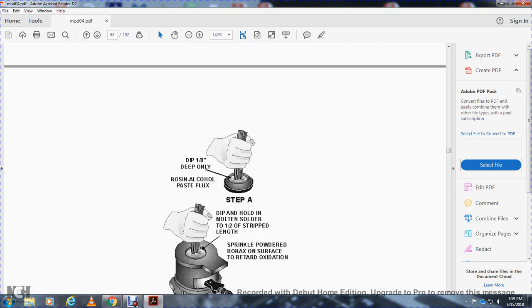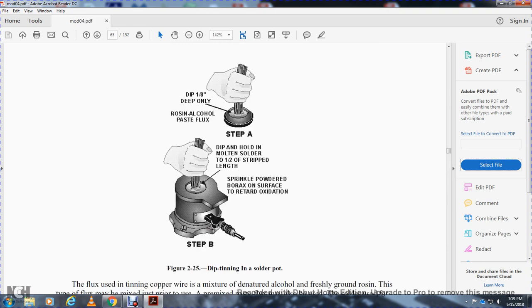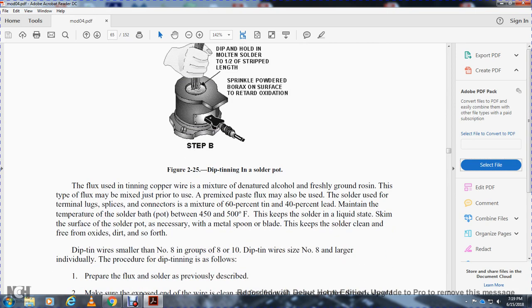Dip 1/8 inch deep in the rosin alcohol paste flux, and then hold the molten solder to half the strip length. Sprinkle powdered borax on the surface to retard oxidation. Step B, dip tinning in the solder pot. The flux used in tinning copper wire is a mixture of denatured alcohol and freshly ground rosin. This type of flux may be mixed just prior to use; a premixed paste flux may also be used.